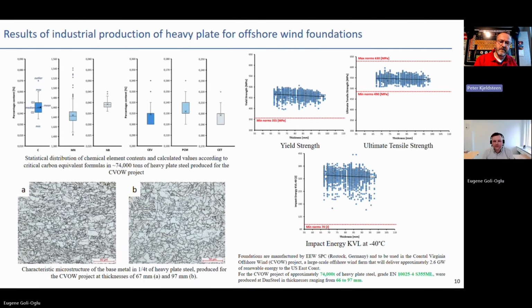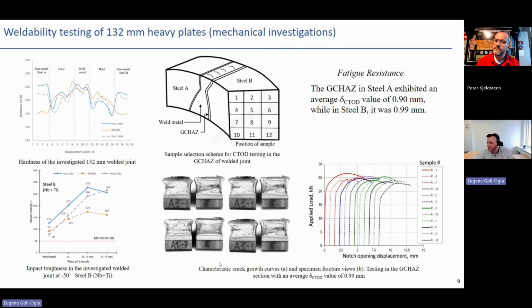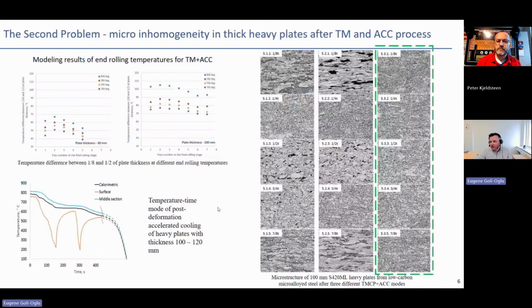And is there anisotropy in thick plates, or is that only seen in thin plates that are cold rolled? Yes, there is also anisotropy of properties, and the thicker the plate, the more complicated it is to make deformation, because the peak of deformation will be at 1/8 of plate thickness, and then it will be lower and lower. And then you have to combine both technology and chemical composition, aiming to achieve the best uniformity of the microstructure possible, in conditions which depend on thickness and grade of material.